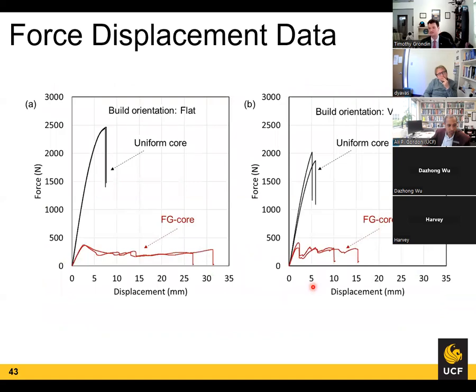So in this data, we've got the force versus displacement for both build orientations. And you can tell that the uniform core shows almost linear elastic until failure over here, and then slightly more deformation over here. We noticed throughout the course of all 8 experiments that we had a clear differential between the flat printing build orientation and the vertical build orientation. And in the graph down here, you can see that there's clearly much more energy absorption in the functionally graded core. And then even in the uniform core, when it snapped, we were below 5% elongation here, which shows that this might be a brittle material. And then this could be a ductile material over here with the yielding zone and the actual break.